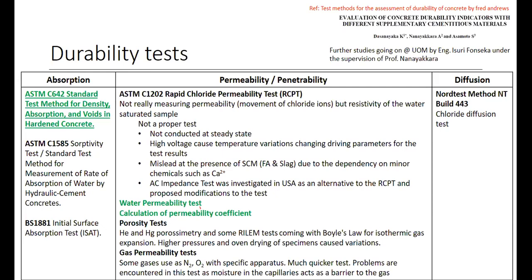If it is a dam or water retaining structure, it is better to go for a water permeability test. Those are more accurate when compared with other test methods. Or if it is dealing with a submerged structure within a marine environment, it is better to go for both absorption and permeability tests.